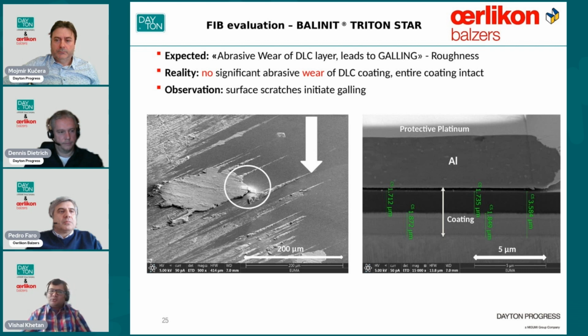Point number one. Point number two, we always see that the coating is intact. It's always the surface where the sticking takes place, and hence the tool is protected. We do not damage the tool right away. One can always clean up the aluminum if the galling is heavy, or we can change the coating type. But we always see in aluminum forming and cutting that in the majority of cases, once you use a coating, the wear reduces significantly, and that's how we cooperate with Dayton to give these coatings on top of their tools, to give our clients the best performance they need in terms of quality of product produced, in terms of the lifetime of the tool, and in terms of better machining time and processes with lesser downtimes.